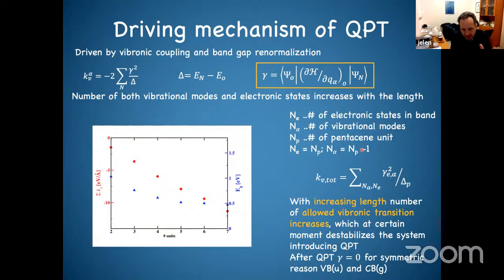Okay, so this is the reason for what we see, and you can now understand that this Jahn-Teller effect, and this kind of symmetry which you have inside the band, is ruling your phase transition. I think this is a nice example that we can also study this quantum phase transition in this π-conjugated system, because these are much simpler in the sense that we don't have to deal with spins, etc. So the systems are much easier to understand, if you want.